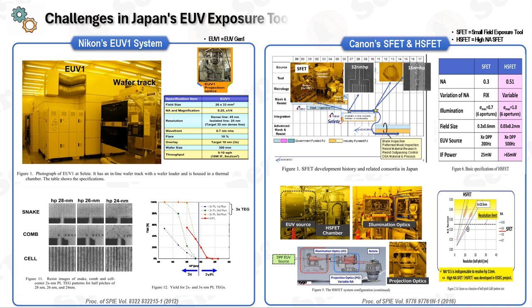Nikon and Canon, two tech giants from Japan, ventured deep into the realm of EUV exposure tool development. Nikon's EUV1 tool marked an advancement in the field. It utilized full-field projection optics, achieving a precise focus with its six-mirror system of NA 0.25. Nikon also highlighted the potential of reaching NA 0.43. They effectively addressed carbon contamination using UV dry cleaning and resolved mirror oxidation with an improved capping technique. The tool was powered by a xenon-fueled DPP-type EUV source, producing a solid 100 watt. In 2008, Nikon reported a successful electrical test for a 32 nanometer line pattern over the full field.